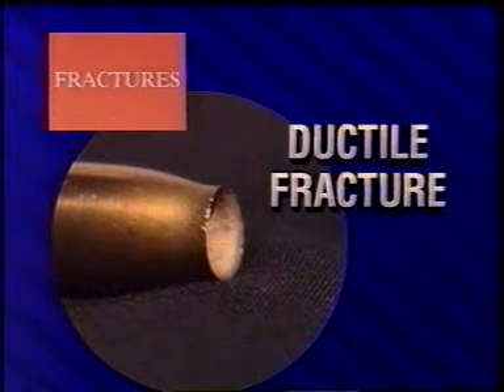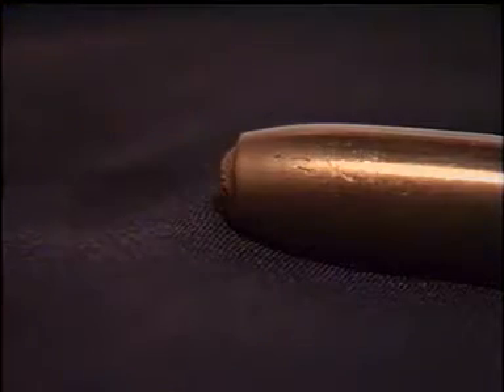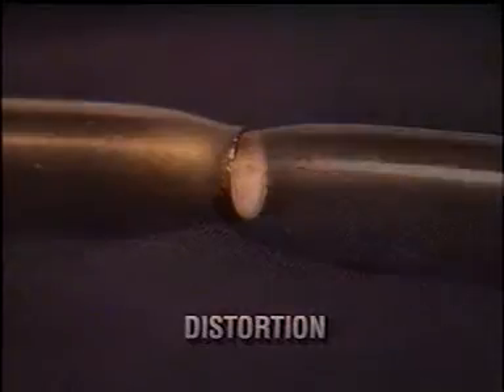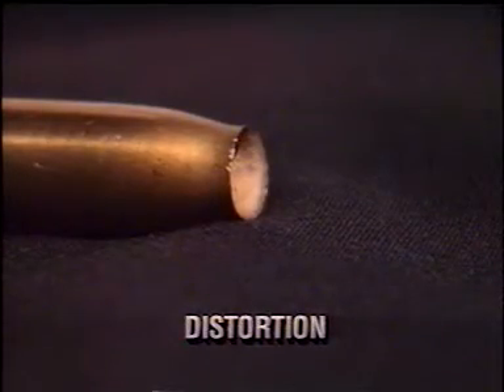Gray cast iron is an important exception to strength and hardness as indicators of the trends most likely to affect behavior in metals. Ductile fracture. One of the first things to look for in a fracture is distortion. Distortion is usually an indication of ductile fracture.